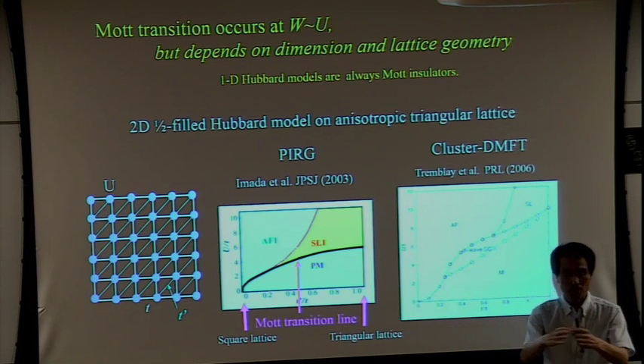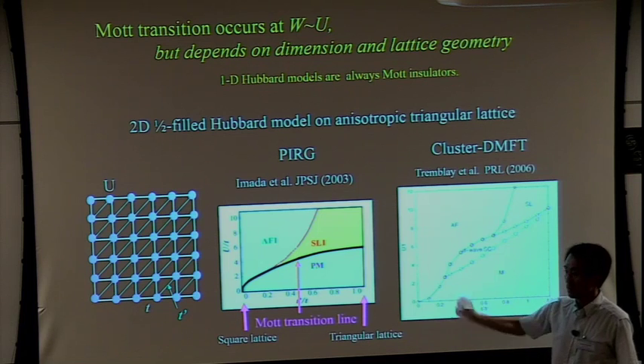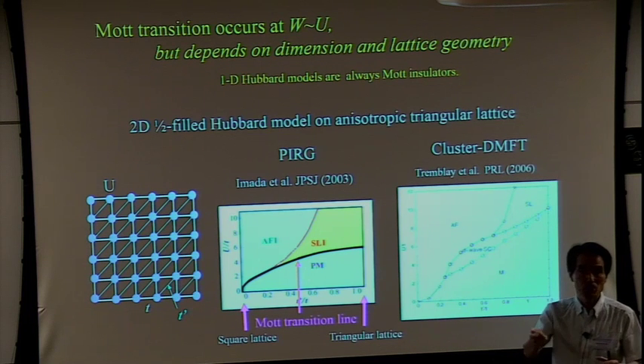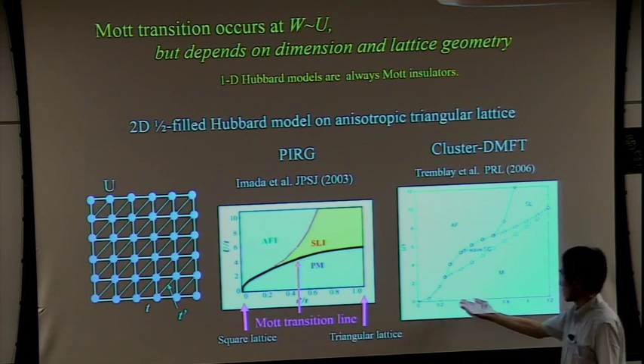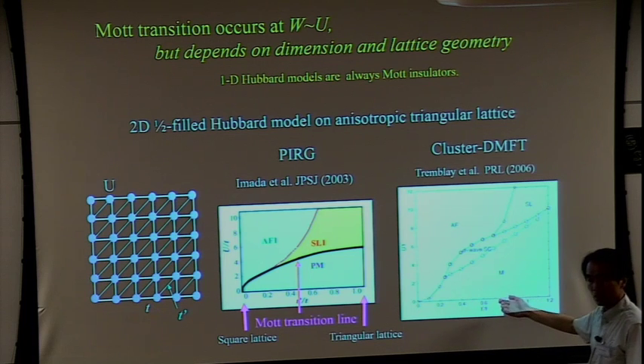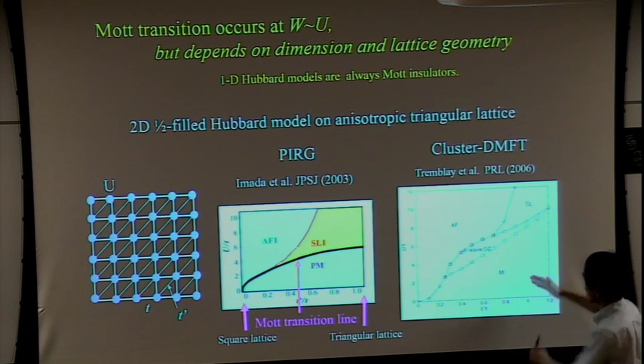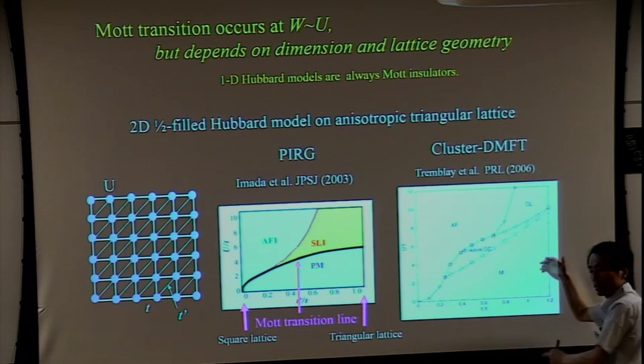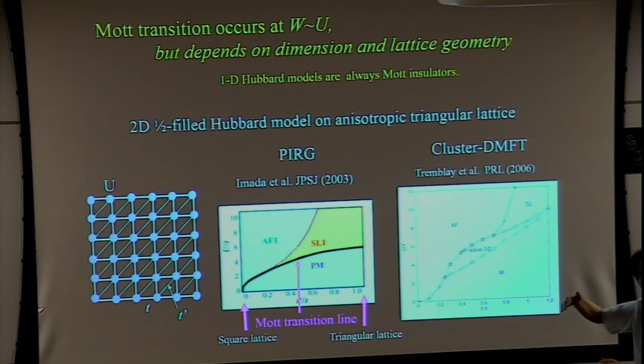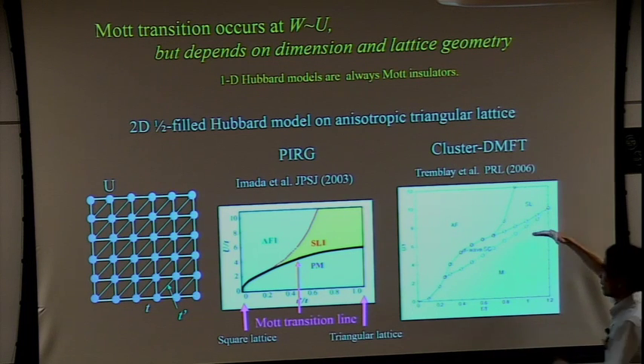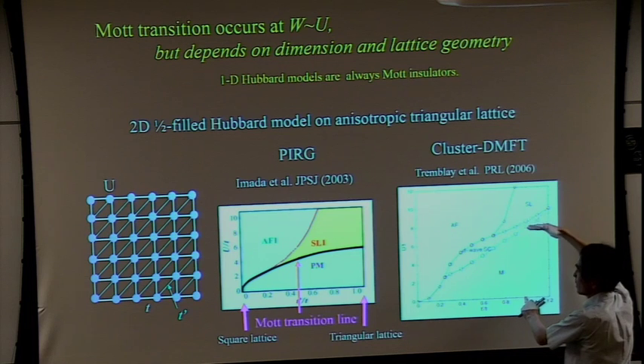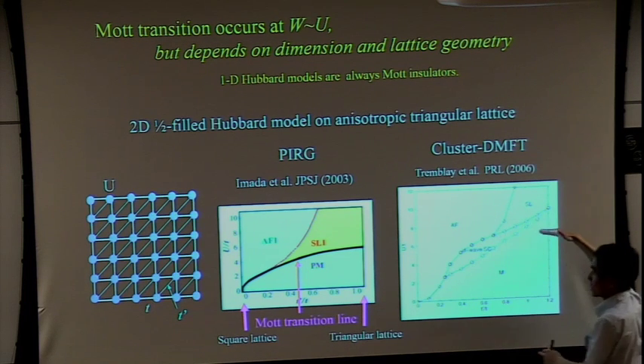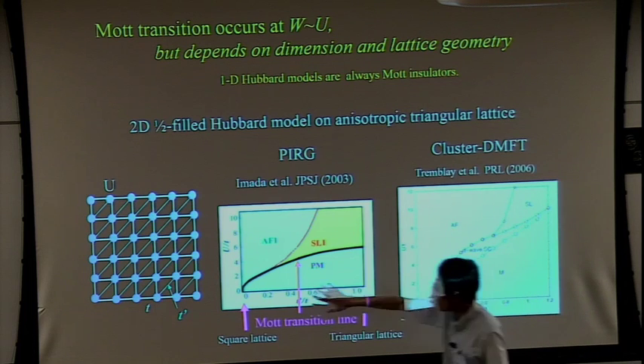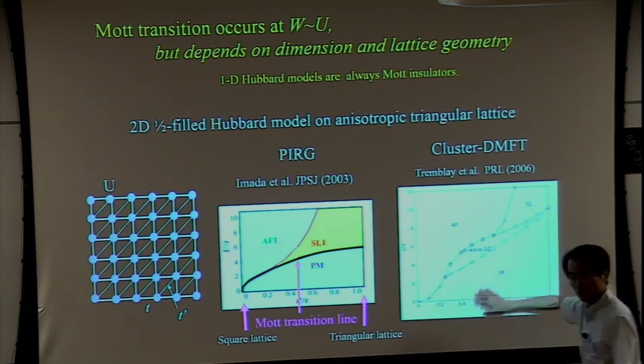The nesting is very good in this case, so infinitesimal U gives Mott insulators. But if the frustration is increased toward the triangular lattice, the Mott transition becomes difficult to achieve up to large values of U over T. But this profile is roughly reproduced.